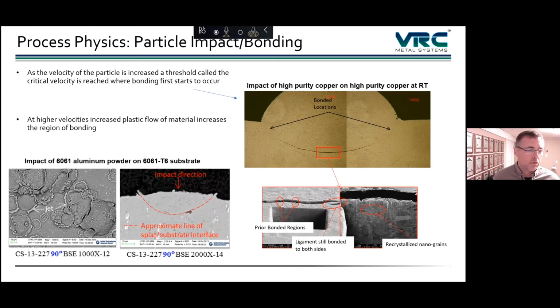So on the top right, you see a copper particle. This is a very large copper particle, and this impacted at a high enough velocity to bond, but just barely. A little bit lower than this velocity, particles were bouncing off, and above this velocity, we get bonding. And you can see where the bonding starts. The bonding starts at the outside edges of the particle. The very bottom of the particle is actually unbonded. Now, if you look very closely, there were bonds that had occurred there, but they broke apart due to the elastic rebound of that particle.